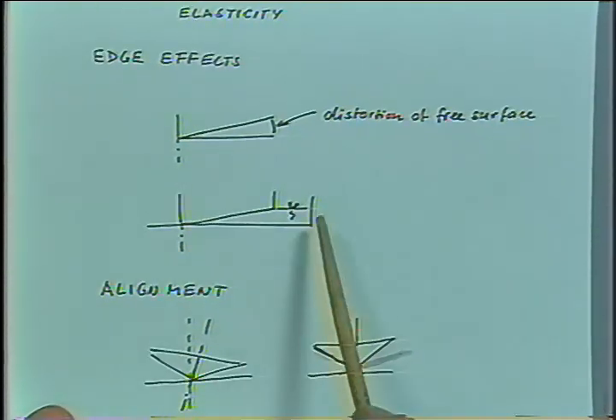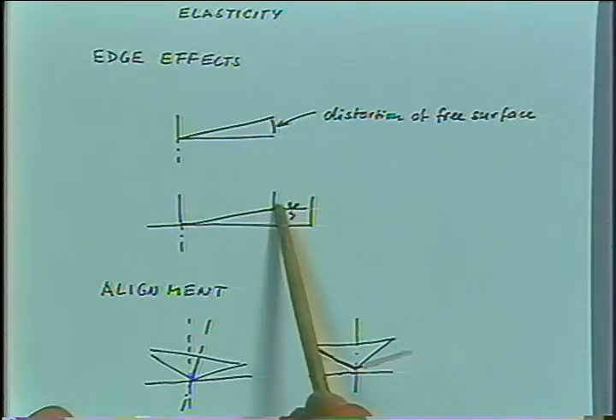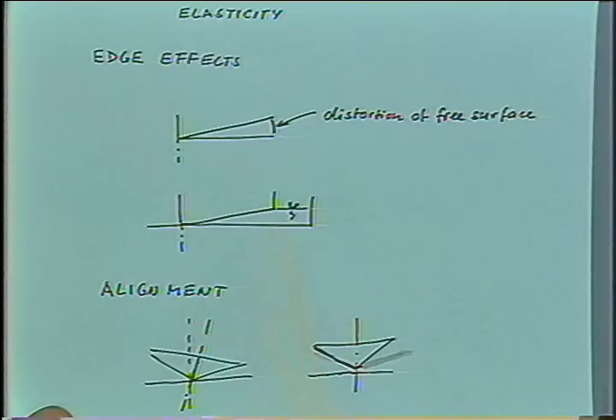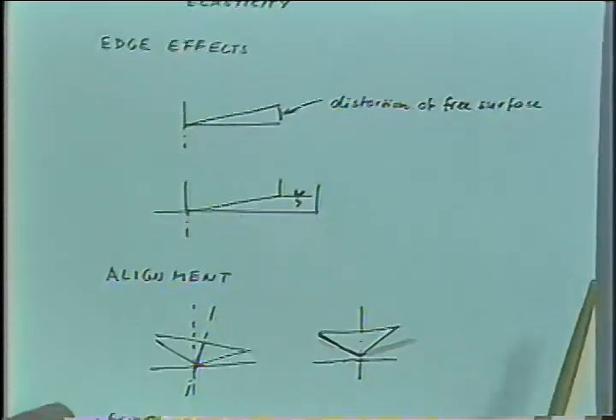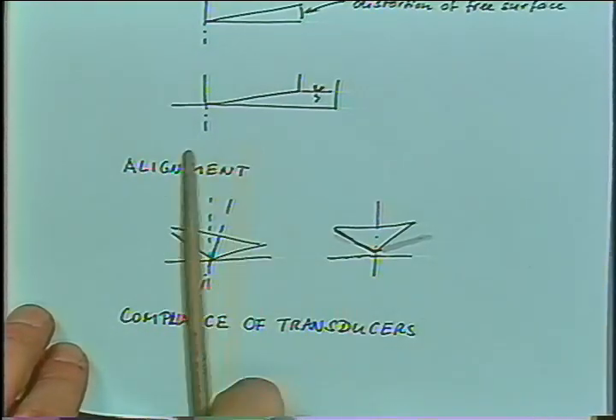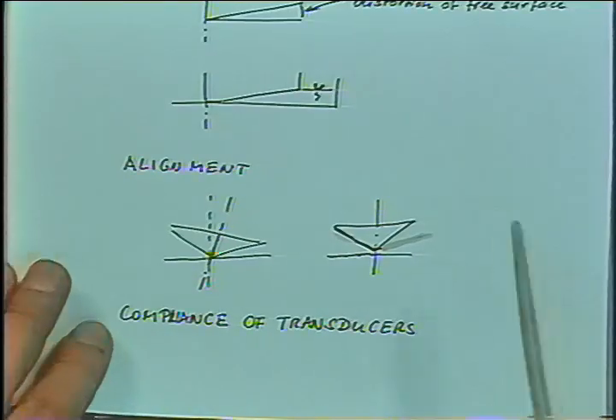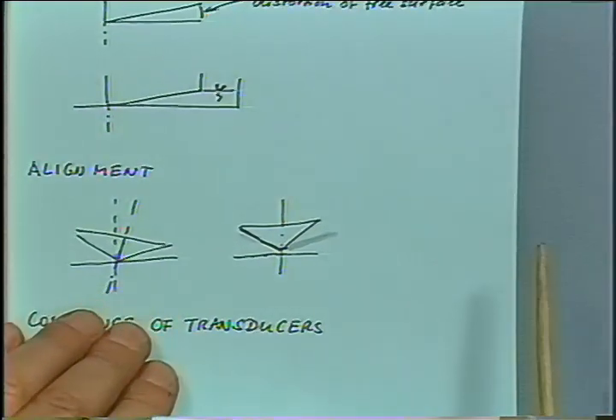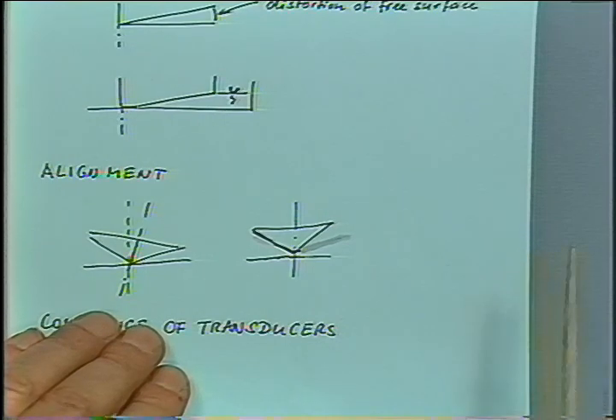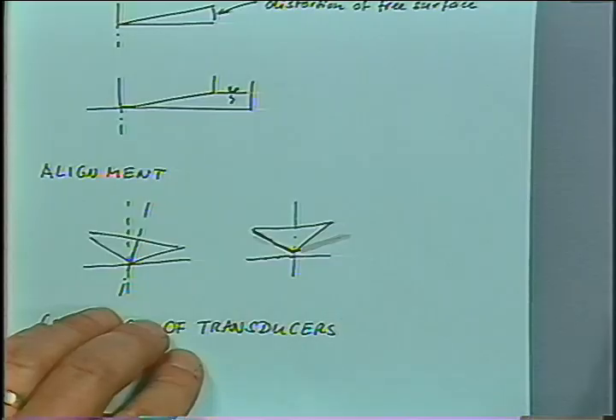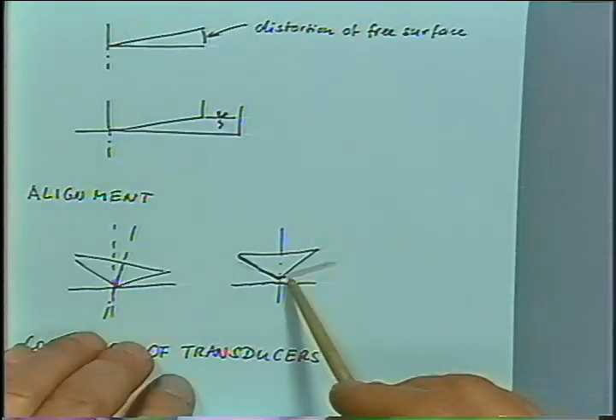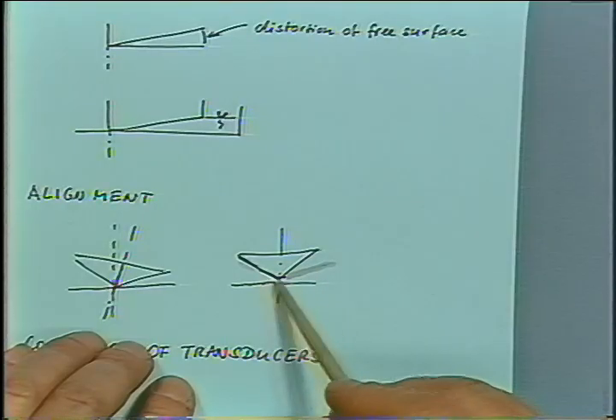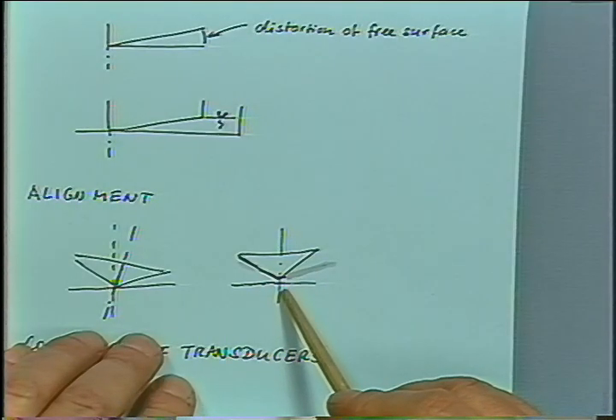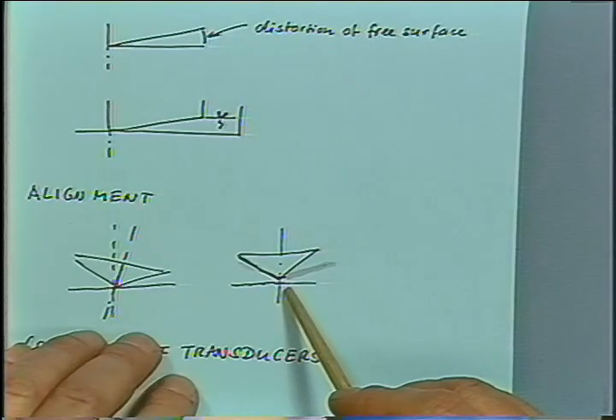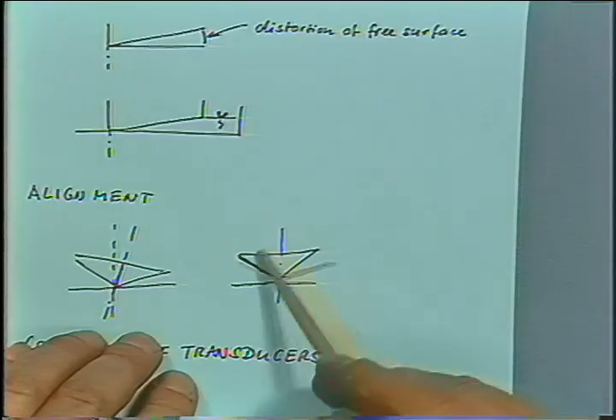In low viscous systems, the sample would not stay in here unless you have a bath of liquid, and that will change the free surface conditions and will give rise to some additional stresses. And then your cone might be at some angle, which I hope it isn't. You can check that. You have to align your rheometer, and there are some tools which you have to use to check whether you are not in that type of trouble. And then you have to set your zero so that the cone is touching the plate at every temperature level you're measuring, because the temperature gradients in the machine will give rise to various expansion effects, and you have to accommodate this in a conventional experiment.